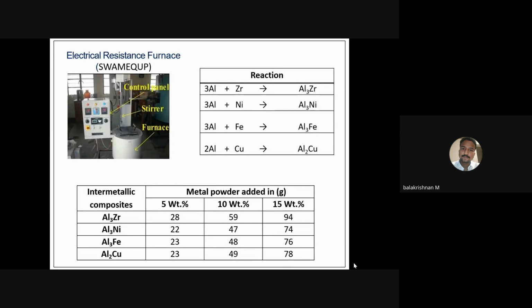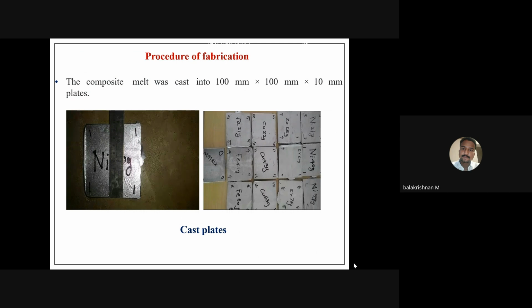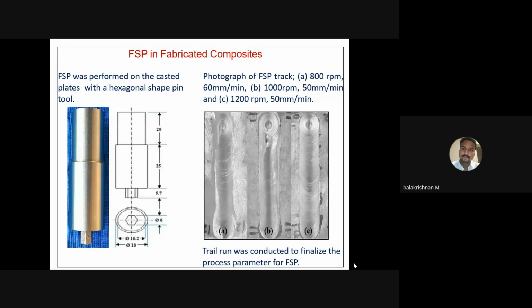Here, the reactions and metal powder added in grams. Then fabricated composite, then tool used for this process. Actually, for this process, a hexagonal pin profile tool was used with a shoulder diameter of 18 mm.